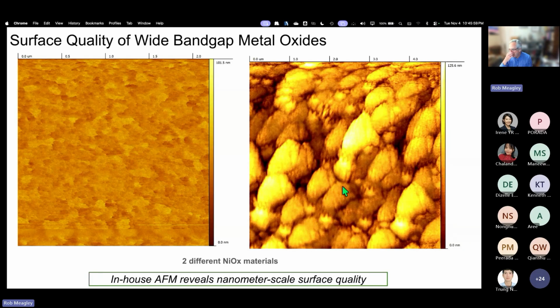On the right, you see a very different nickel oxide on FTO being put down, and a much more complex topography as a result. Although both of them have relatively similar peak to valley distances, the overall shape and nature of the surfaces are quite different, and you might expect that they might have different optical and electronic properties as a result. There's just no substitute for resolution, and the resolution from this tool is exquisite.